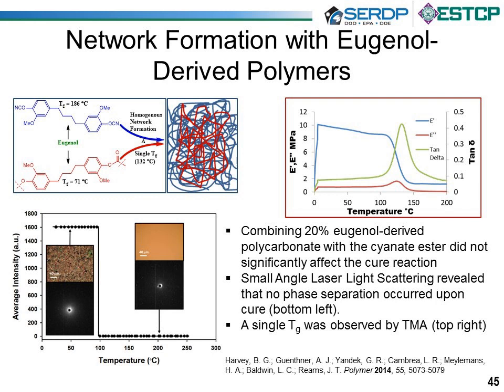And we also ran an experiment on the bottom called small-angle laser light scattering. So initially, when we've got crystalline cyanate ester around, you can see that we have a very high intensity of scattered light. It then melts and forms an amorphous mixture and virtually no scattering. What we would typically expect to see is an increase in scattering as the cyanate ester resin cures due to phase separation. But in fact, we see no phase separation. So there's no phase separation by the SALS experiment. There's no phase separation by TMA. So it suggests that we're forming a homogeneous network, which could be very useful for forming toughened thermoset materials.